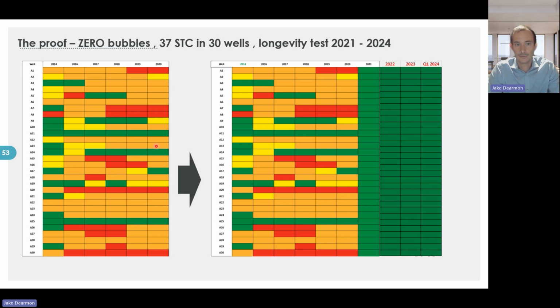So here was a 30-well campaign that we completed in 2021. It started years before that with a lot of the plug and abandonment requirements, some of the testing, alloy qualification testing, actual tool qualification testing, a 2-year field trial. But we can see here on the left-hand side, these wells had previously been abandoned, all 30 of them. And by 2020, we had almost every single one of them having problems. And those problems being pressure at surface from shallow gas formations entering the wellbore.